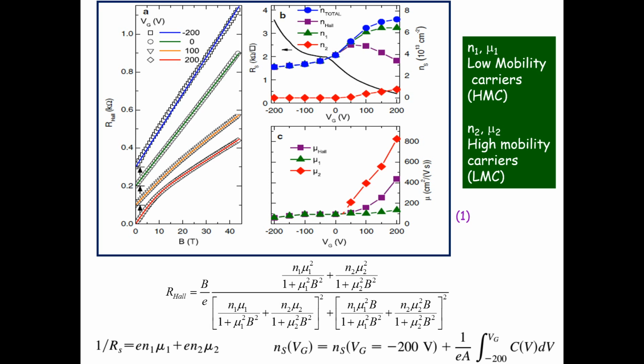So both your N1 and N2 increase, but the Hall decreases when you increase the back gate further, right? The purple curve. Purple curve is the total Hall. Right, so shouldn't that increase because both N1 and N2 increase? This is coming down, and because of the mobilities, you cannot directly translate the two. You cannot directly add the two. Okay, the mobility factor also comes in.